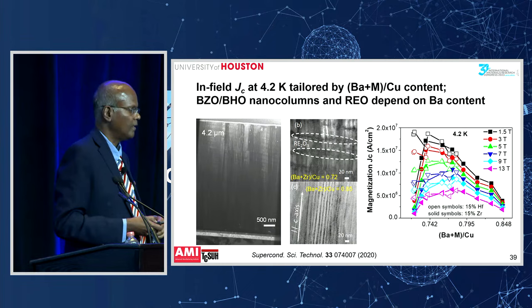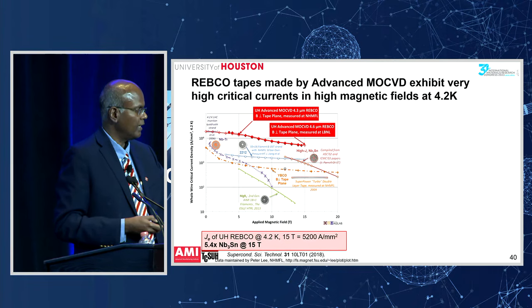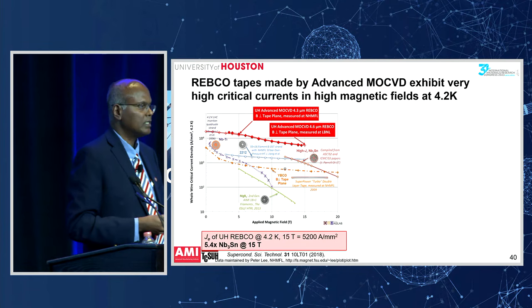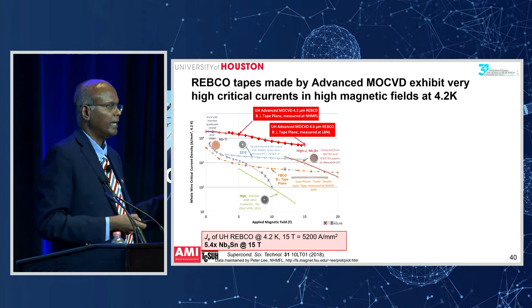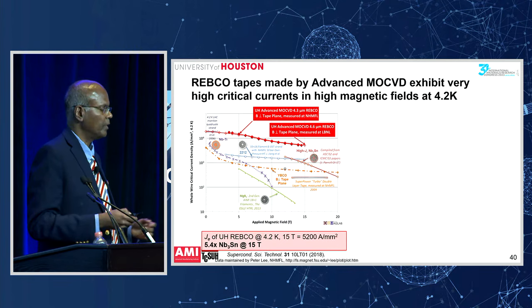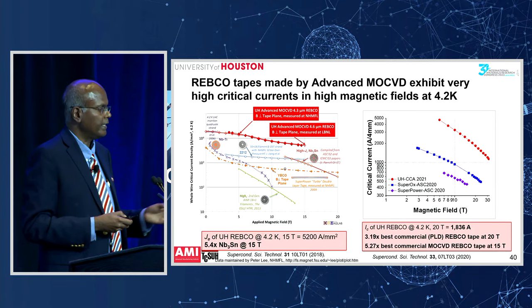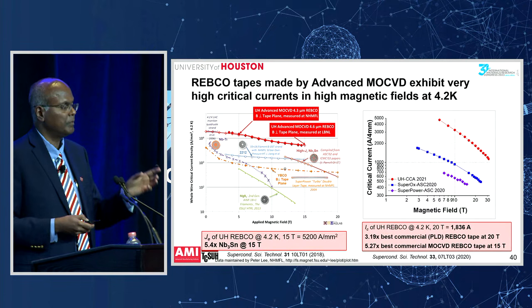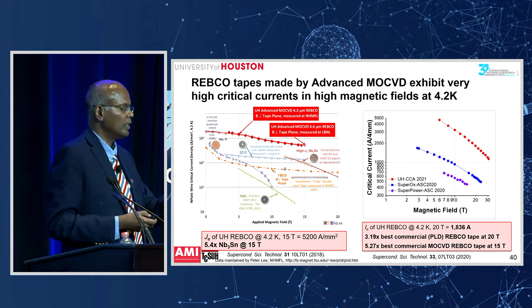And as a consequence of that, you see the performance of the superconductor film in high magnetic fields. It's a busy slide, but just look at what's seen on the top. That's the performance of the superconductor film made by advanced MOCVD in the high magnetic fields. If you compare that to niobium titanium, niobium tin, or the conventional superconductors today, it's much, much higher current carrying capacity. On the right-hand side, the red circles are the performance of the superconductor film made by the advanced MOCVD process, and the blue and the purple are what is made by industry today. So what's made by advanced MOCVD is about 3 to 5 times better than what the industry does today.